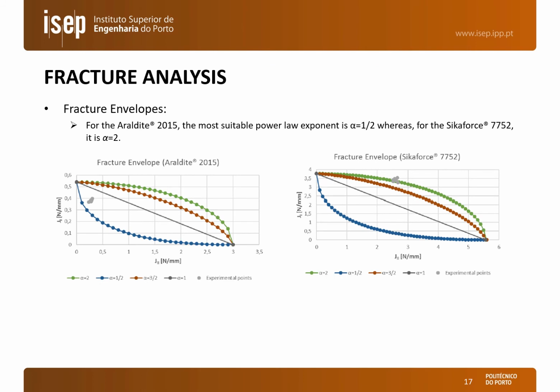Here we can see the fracture envelopes for the other two adhesives. We can see that for the 2015 the experimental points are closer to alpha equals 0.5, although it does not overlap them completely. And for the polyurethane adhesive we have a completely different behavior, as the experimental points are close to the alpha equals to 2 exponent.